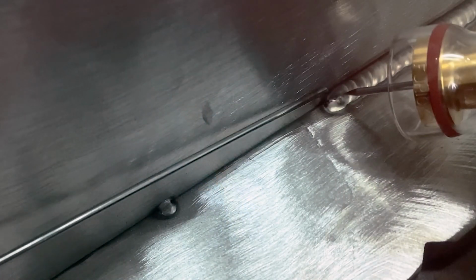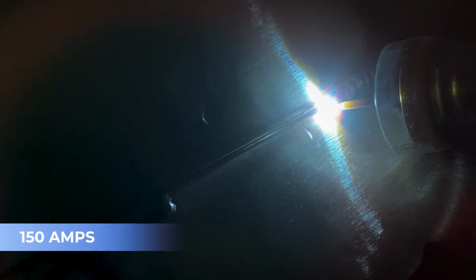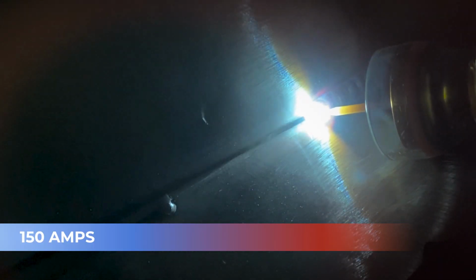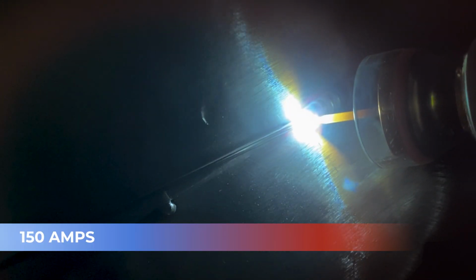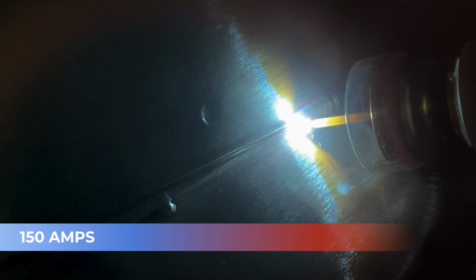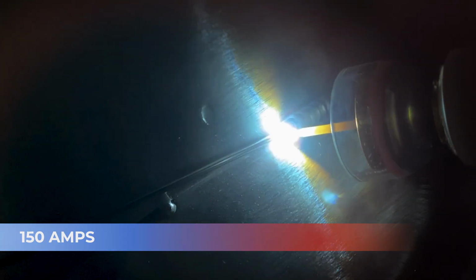I don't have enough amperage. I don't have enough heat. I don't have enough arc force. I don't have enough of all the good stuff to make the business happen and to make a good weld. Moving forward here, the only parameter that's going to change is I bumped it up from 130 to 150 because I knew that everything was too slow. Nothing was flowing. And I can tell immediately that my base metal is being consumed, not creating undercut.